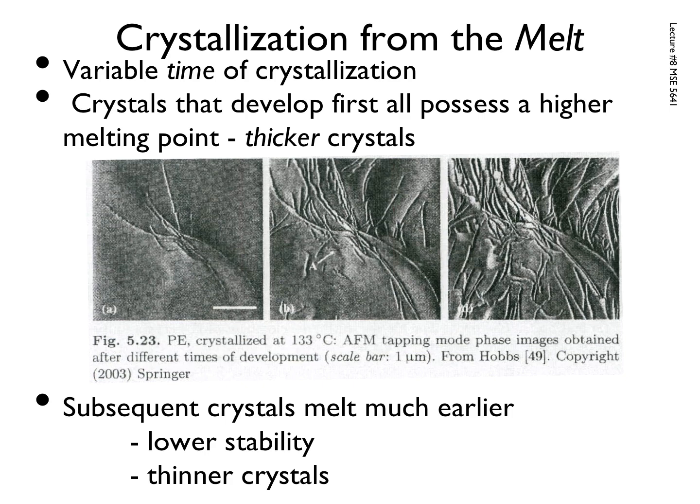All right, so AFM involves taking a silicon nanoneedle and tapping it on the surface or across the surface of, in this case, a polyethylene film as crystallization is going on. And why that works for us here is the crystals, again, this cheat we have of thinking of the crystals as little rocks inside of the relatively soft amorphous phase around them.